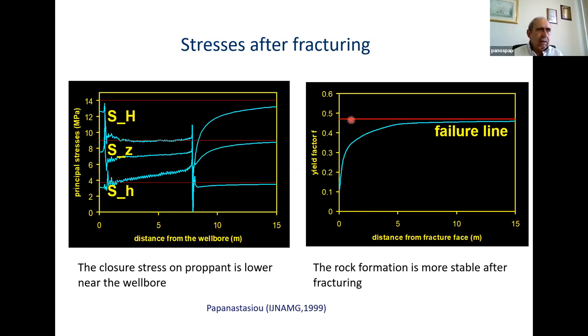Now you can see, before fracturing, the stress state is very close to failure. Now, if we do hydraulic fracturing and allow the fracture to close on the proppant, we push the stresses away from failure. So here, basically, we are just on the fracture surface. You can see that the stresses move away, far away from the failure line. And this is as we move to the distance perpendicular to the fracture surface. So far away, it's like not seeing the hydraulic fracture. But very close to the fracture, we push the formation away from failure.